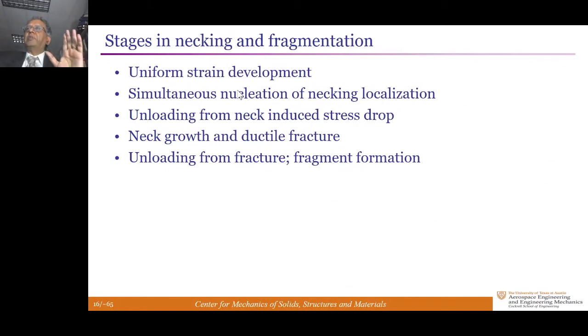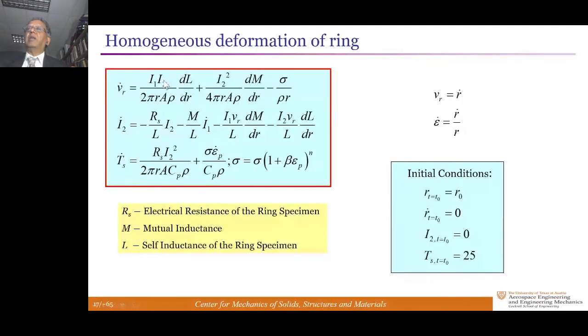Analysis of this up to the point of onset of necking is very straightforward. First line says F equals MA. The force comes from the interaction of the currents between the coil and the specimen. Its resistance comes from plastically deforming the material as it expands out. The second one is the rate of change of current, and this depends on the specimen moving away from the coil as a function of time. And the last line indicates temperature effects and so on. But you can solve this. This is a simple first order ODE.